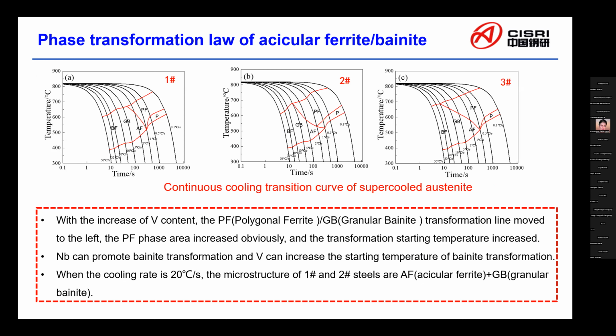With the increase of vanadium content, the polygonal ferrite and granular bainite transformation line moved to the left, the polygonal ferrite area increased obviously, and the transformation starting temperature increased. Niobium can promote bainite transformation, and vanadium can increase the starting temperature of bainite transformation. When the cooling rate is 20 degrees centigrade per second, the microstructure of number 1 and number 2 steels are acicular ferrite and granular bainite.